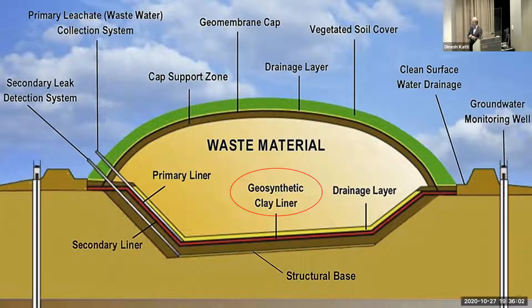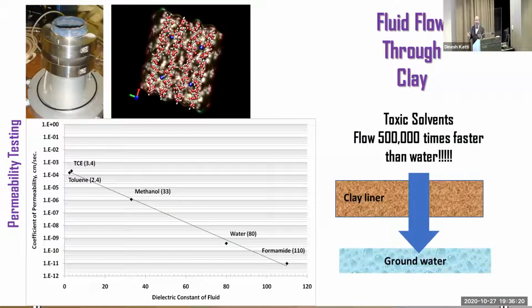So we wanted to see how the fluids which are typically in a landfill are interacting with the clays in the clay liner. And in order to do that, first we had to design a new device because there was no device available to do some very precise calculations of fluid flow for swelling clays or expansive clays. And so on the left-hand top, you see this new device which we designed and fabricated. And then below that, you see a plot which shows the results from those experiments. And I'm going to try to explain those results to you.